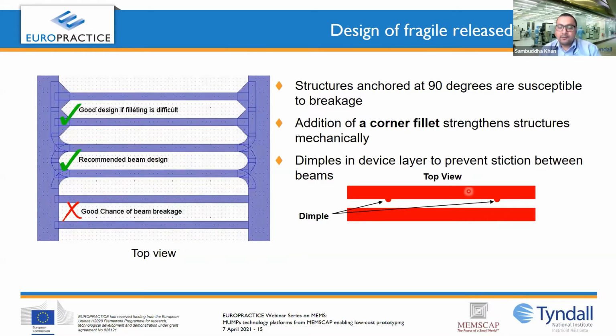Again, if you have multiple beams in parallel and they are very close to each other, it is recommended that you incorporate some kind of a dimple here, so that if by any chance they come close to each other while releasing, they don't stick to each other, because the surface area is reduced and they will not stick if you have dimples between the two parallel beams.